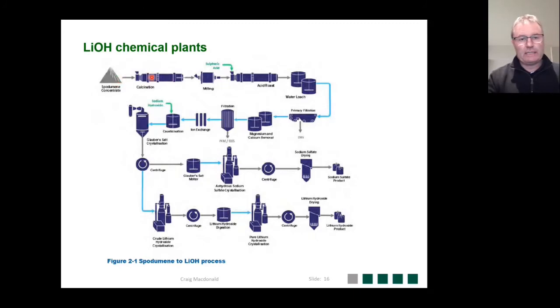Spodumene is fed into a rotary kiln and calcined at a temperature of around 1000 degrees C. If you recall earlier, the natural crystal state of the spodumene is an alpha crystal state. It's converted into a beta crystal state. The solid is then milled, and then sulfuric acid is added and it is introduced into a second rotary kiln for an acid roast. The solid product from the second kiln is then introduced into a water leach, and the lithium and other metals go into solution.